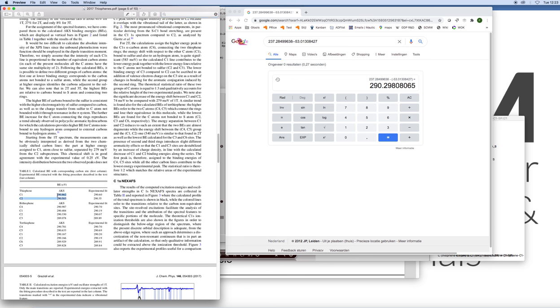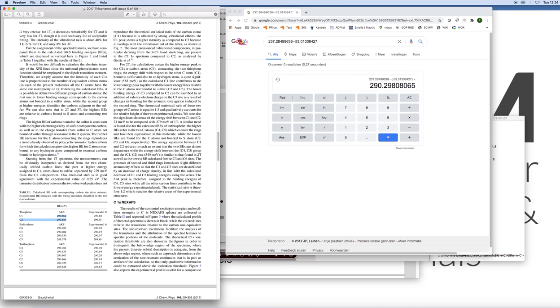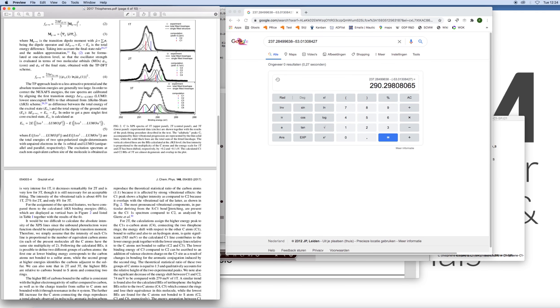Actually, in this paper, they also have a difference of around 0.3 eV, but it's slightly off from the experimental results. So actually, in our case, we're a little bit closer to the experimental fit. And that's why, I think, in this case, they also mentioned that they shift the spectra by minus 0.2 eV. That's not uncommon for XPS as well as NEXAFS and XANES calculations, where the absolute energies can be a little bit off. That's due to the Zora relativistic Hamiltonian. You can also use X2C. Usually, it gives slightly better absolute energies. But in general, the relative spectrum, which is beautifully reproduced here by these calculations, is pretty well reproduced by just regular scalar Zora.